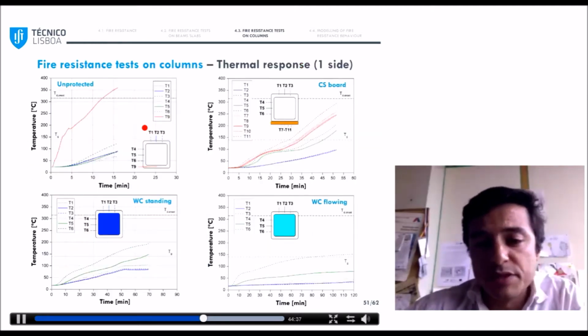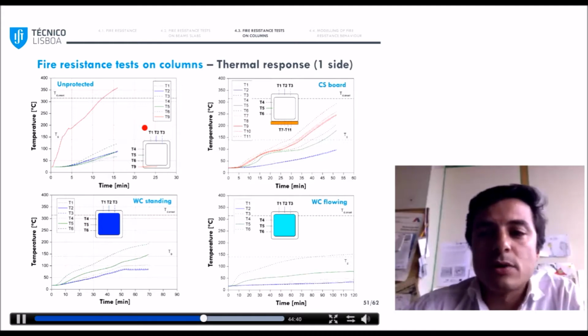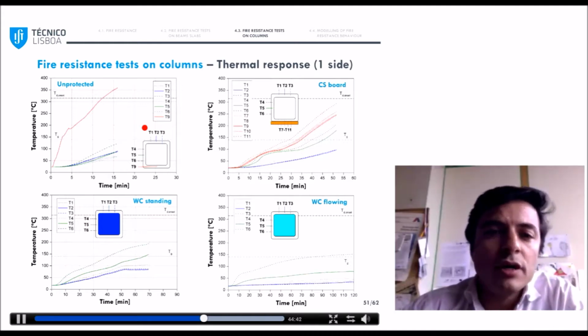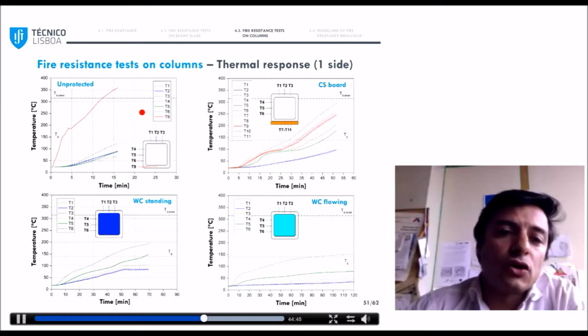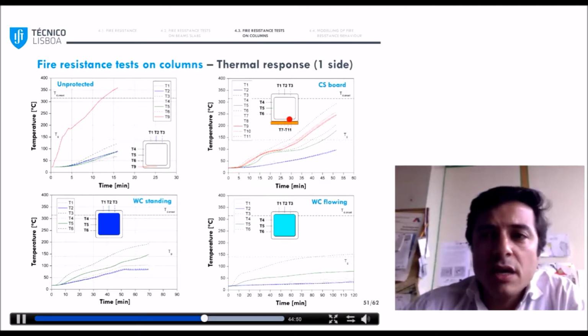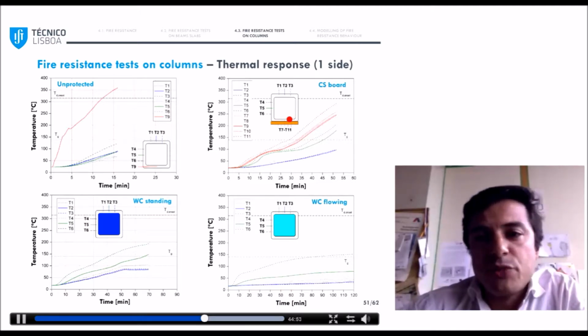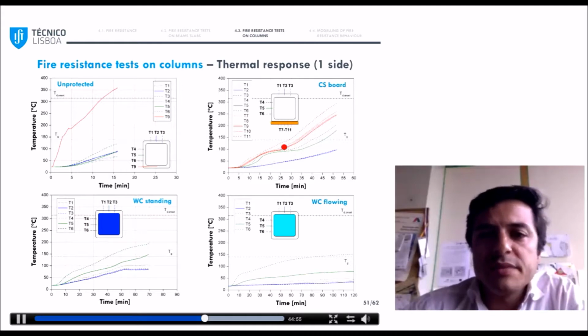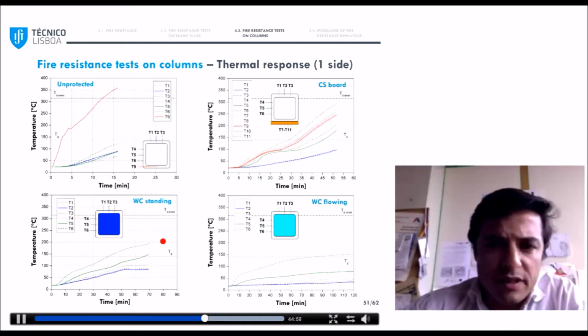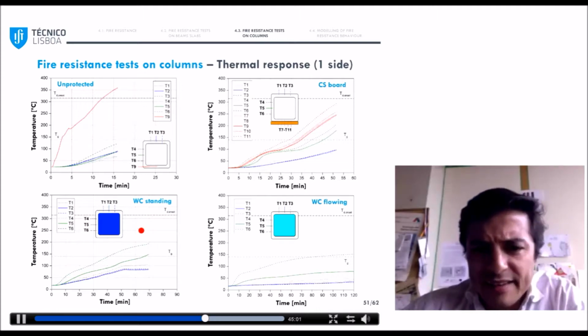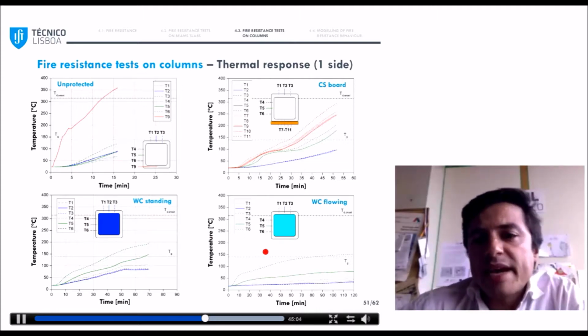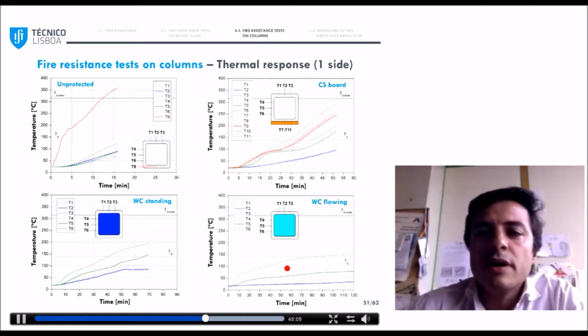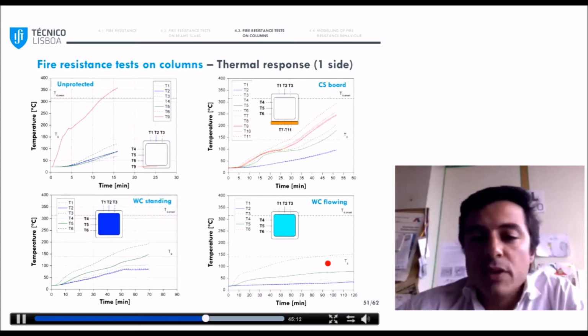For the thermal responses, you can see here the results for one side fire exposure. For unprotected columns here at your top left, and with calcium silicate protection, the results were pretty much comparable to those obtained for the beams. Water cooling in the bottom, either standing or flowing, as expected, conferred very effective thermal protection, especially with the flowing water.